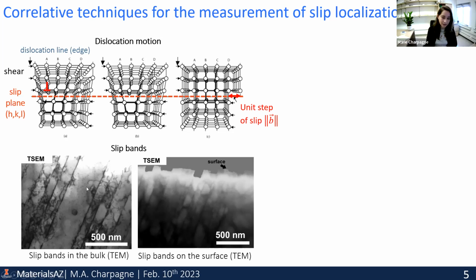And when we look at slip bands, there are several techniques that we can use to look at them. Here is transmission scanning electron microscopy. This is the modern technique, essentially STEM, but in the SEM, and you can see your dislocations through a thin foil. Here the slip bands are those elongated features where many dislocations have been gliding. Here I've shown the process of one dislocation creating one unit step. But of course, if you have collective motion of dislocations onto a similar slip plane, then you get a higher step. So by measuring this step, you can back out how many dislocations actually traveled through the slip band.